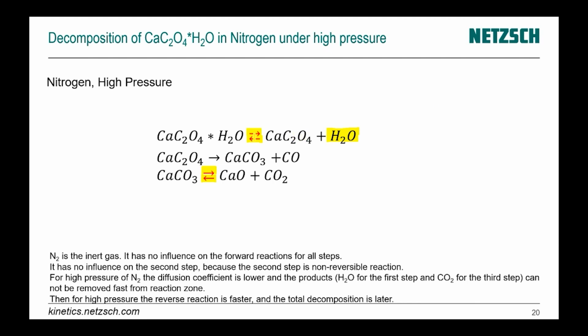And therefore, for the higher pressure of nitrogen, the backward reaction will suppress the total decomposition step number 1. For the second step, nothing happens. We have here only a forward reaction and no backward reaction, and it is not important if we have a higher concentration of CO in the reaction zone or not. We have no backward reaction, no reverse reaction, only the forward reaction. For the third step, it happens exactly the same as for the first step. We have a backward reaction, and for the higher pressure of nitrogen, we have a higher concentration of carbon dioxide in the reaction zone, and then we have the reverse reaction.